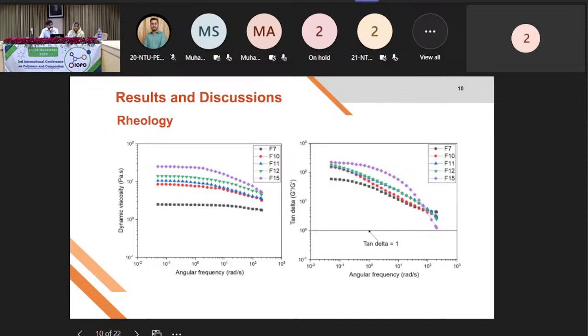Regarding the rheology, it is observed that with the increase in polyvinyl alcohol levels, the viscosity of the material increases. It is also observed that with the increase in shear rate, the overall viscosity decreases.